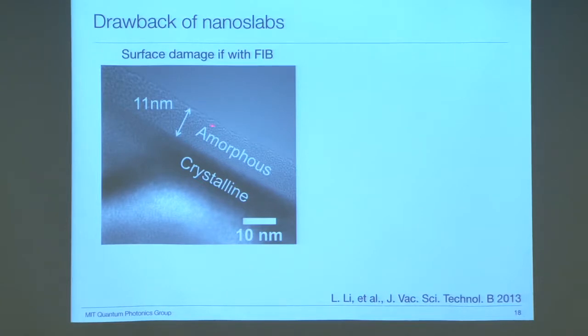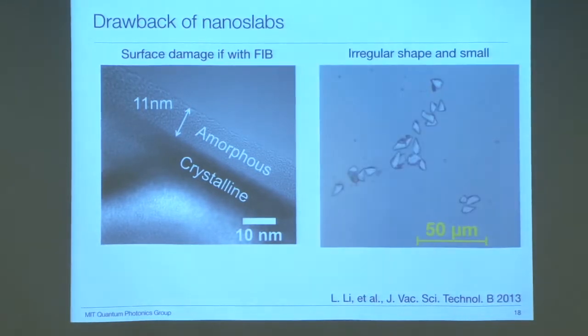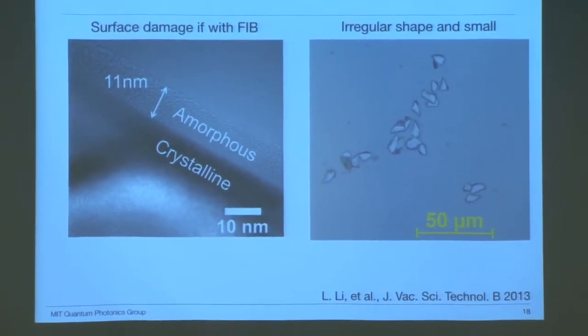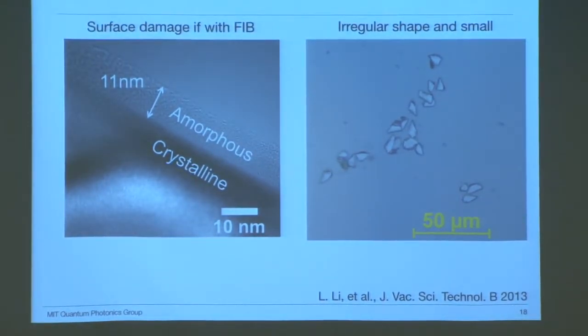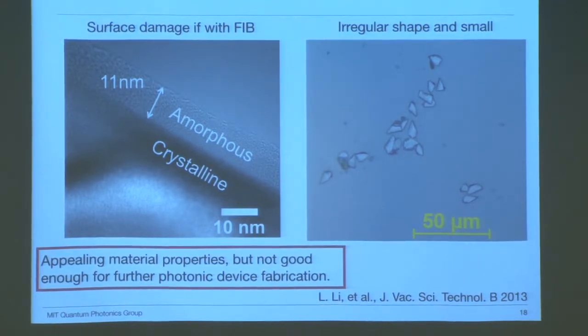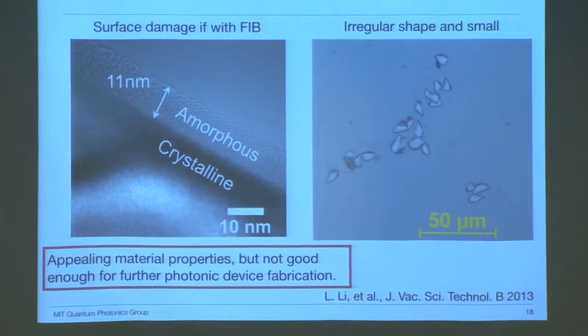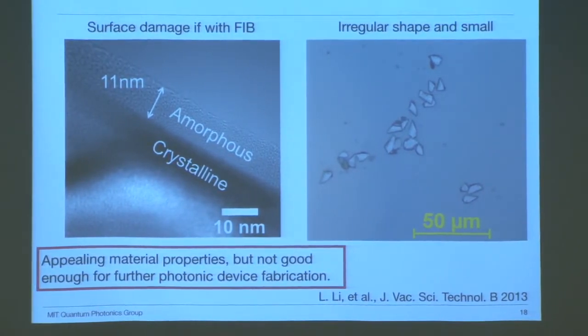We zoom in and examine the edge of the diamond membrane milled by FIB using a transmission electron microscope. There is an amorphous layer that is about 11 nanometers in thickness. This amorphous layer scatters light randomly and prevents the cavity resonance from forming. These diamond membranes are also of irregular shapes and were no more than 20 microns in lateral dimensions. In summary, these diamond nanoslabs have good material property, but they are still not good enough for further photonic device fabrication.